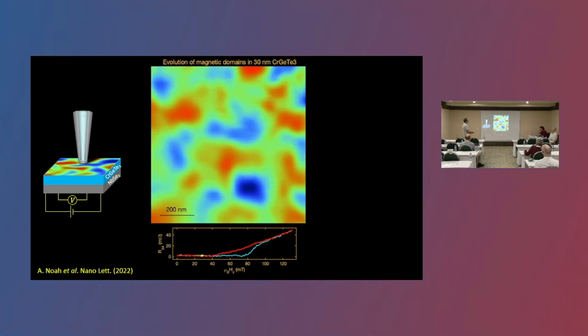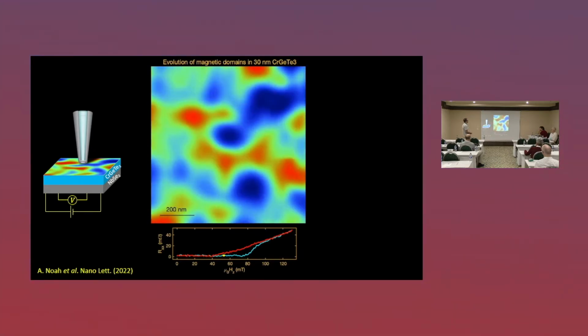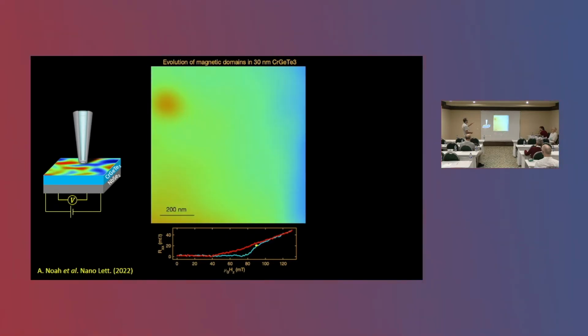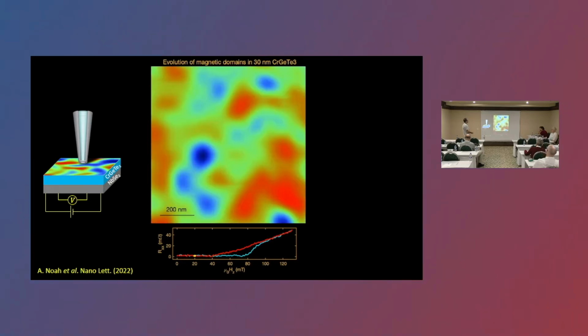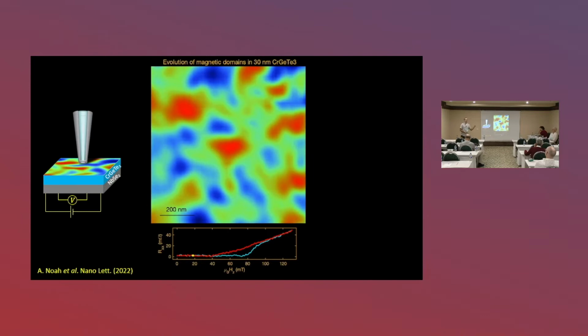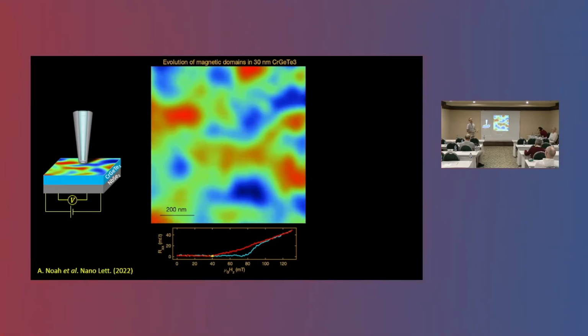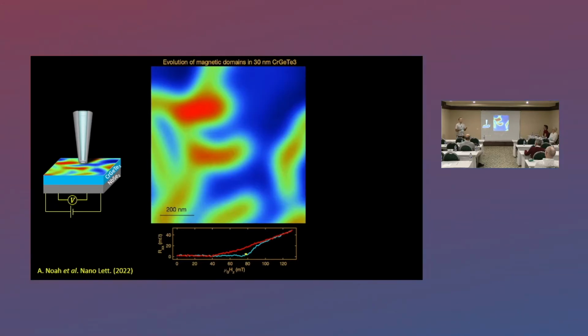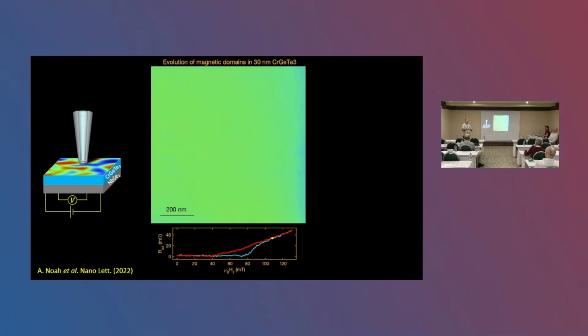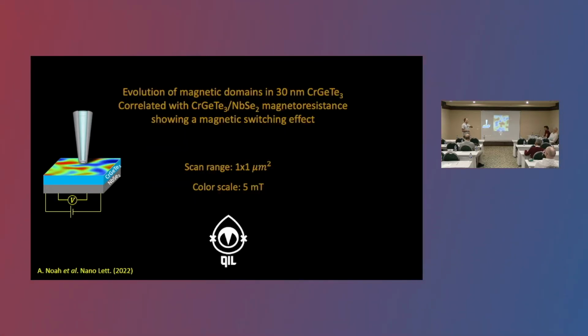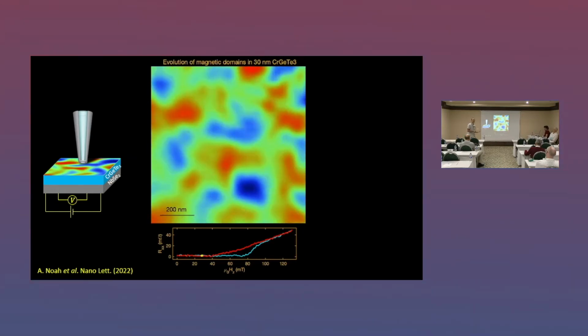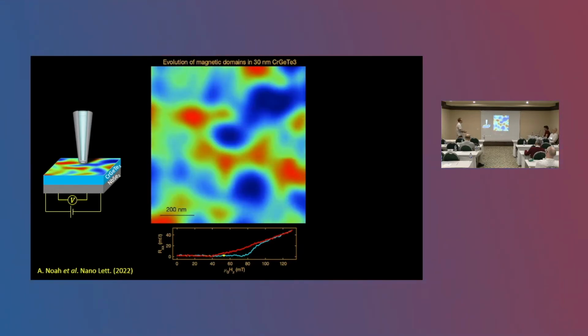So I'm raising the field here. You see this magnetic structure is evolving, and at some point it becomes very flat. This is where the resistance starts to go up. On the way down, the magnetic domains appear and coincide more or less with the zero resistance state. And we interpret this, as vortex physicists, as a pinning potential. If you have a very disordered magnet with a very non-uniform pinning potential, it pins vortices very efficiently, whereas if you are fully magnetized, then the pinning potential becomes very flat and flux flow can happen very easily.